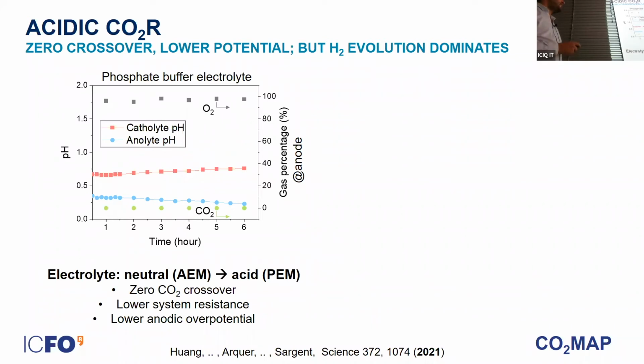You see here that when we operate the system in a phosphate buffer electrolyte with a pH around 1, there is almost no CO2 detected at the anode side. So there is no crossover, which means that CO2 is not converted into carbonate in the first place. And you can see also that most of the gas that we have, 100%, is oxygen. So this system seems very promising. Okay, we have zero crossover.